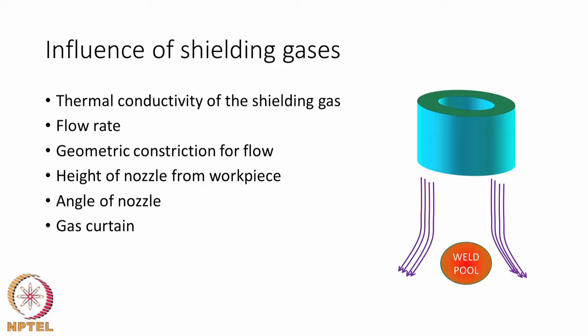And there are situations where you may have a gas curtain separating the nozzle and anything else behind the nozzle. You may have a situation where you want to remove the heat through a liquid nitrogen jet behind the welding torch, and if you do not want the nitrogen to mix with the weld pool, then you may want to have a gas curtain, again made of argon, in between. Such gas curtains also remove heat and play a role in the heat source distribution. So, we must also know whether gas curtains were used or not, and whether they have played a big role or can be neglected. But we must be conscious of all these influences that shielding gases will have on the heat source distribution.